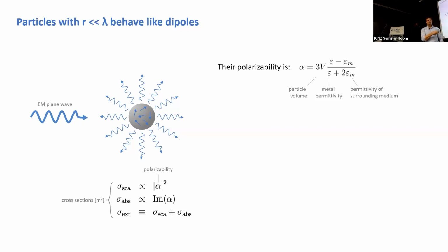So if we say vacuum, the permittivity of vacuum, this would be 1, so this would be epsilon minus 1 over epsilon plus 2. Now what happens is that metals can have negative permittivity, and that's really a characteristic of metals. So there are frequencies or wavelengths of the electromagnetic radiation for which this permittivity of the metal can be -2 in vacuum, or -2 times the permittivity of the surrounding medium if you're not in vacuum. And this is the so-called Fröhlich condition.